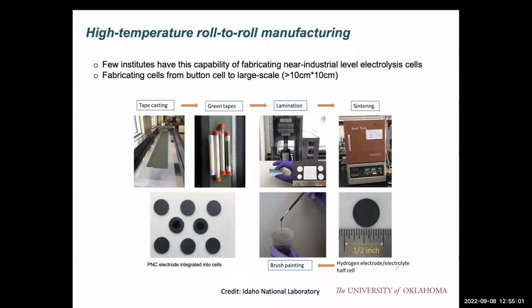After this material is synthesized, we can manufacture the SOC device. Normally, we use a roll-to-roll manufacturing process, which has been established at Idaho National Lab, which was my previous working place. So we use this capability to manufacture the green tape of the different components, such as the fuel electrode tape and the electrolyte tape. We can fabricate this kind of green tape with different thicknesses. And then we laminate different green layers together to form one integrated layer, and then we put it into the high temperature sintering furnace to densify the electrolyte.